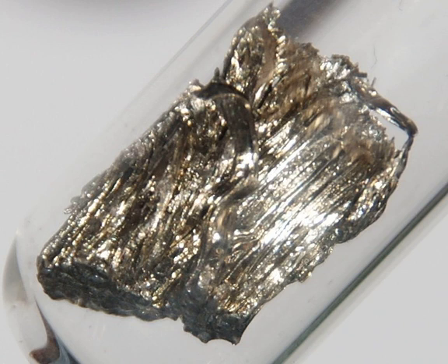Borides. Sintering powders of samarium oxide and boron, in vacuum, yields a powder containing several samarium boride phases, and their volume ratio can be controlled through the mixing proportion. The powder can be converted into larger crystals of a certain samarium boride using arc melting or zone melting techniques, relying on the different melting and crystallization temperature of SmB6, 2580 degrees Celsius, SmB4, about 2300 degrees Celsius, and SmB66, 2150